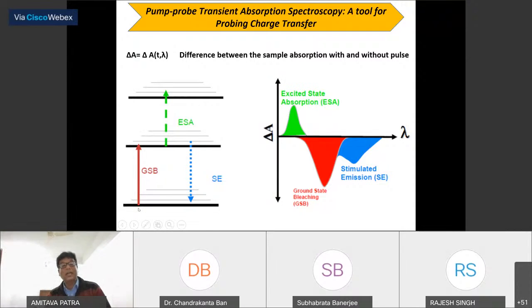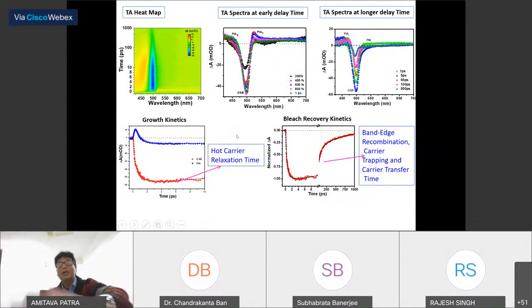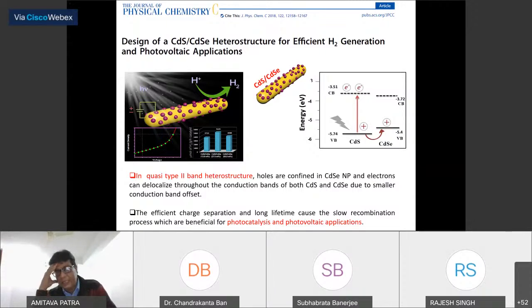By using the photon energy, it goes from the ground state to the excited state. This is the ground state bleaching, and we try to understand this bleaching kinetics. I don't want to go into the detail, but this is the kinetics from the transient spectroscopy. If you have the growth kinetics, then you can understand the hot carrier relaxation process. If you have the bleaching recovery kinetics, we can understand the recombination process. I'll not go into the details, but this is one example recently published two years back.